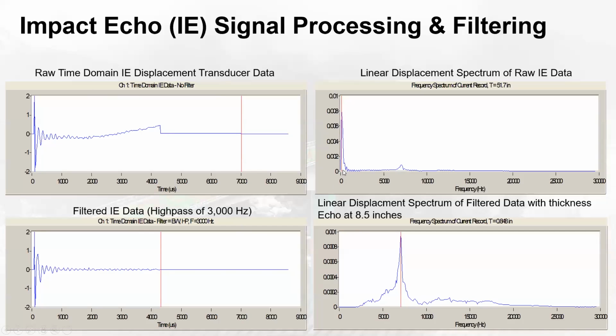If you used an accelerometer, you would not have that resonance, but generally we use displacement transducers and accelerometers for really thick concrete. So you see a resonant peak now clearly at about 7,000 hertz that corresponds to 8.5 inches for depth equals the factored impact echo velocity, where 0.96 is the number for a slab or wall shape, times compression wave velocity divided by twice the echo frequency. That corresponds to the 8.5 inches.